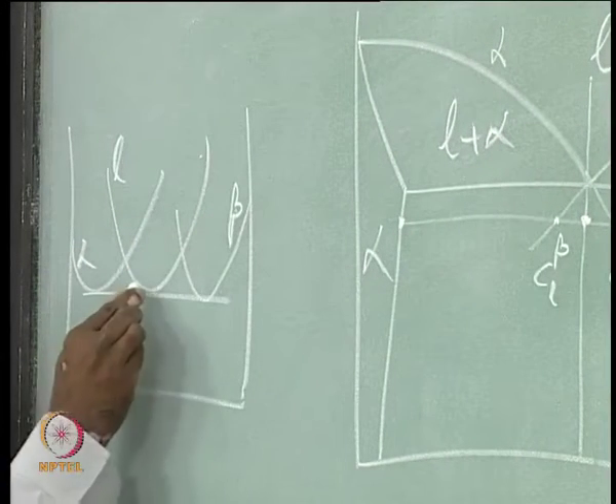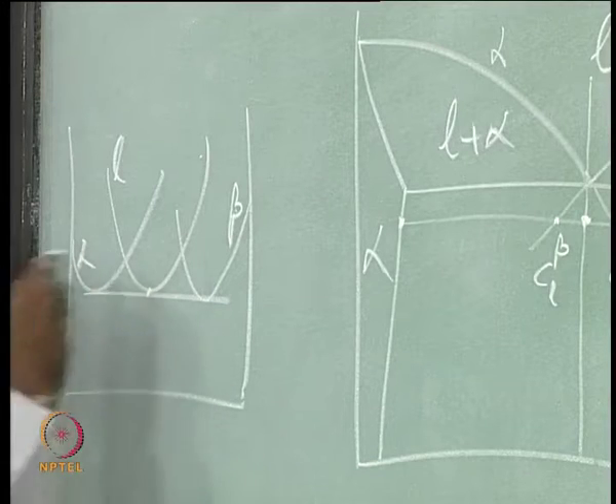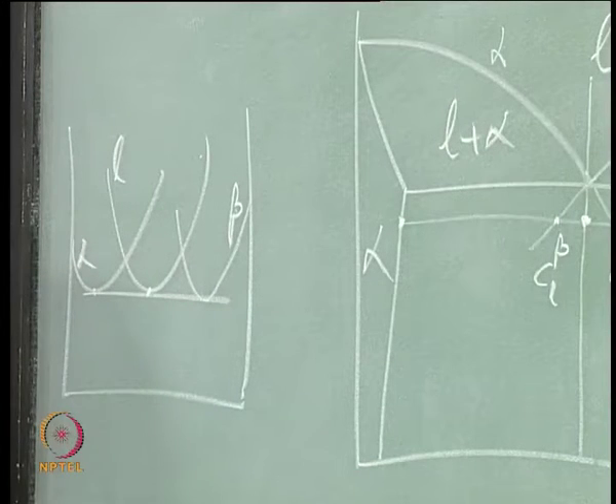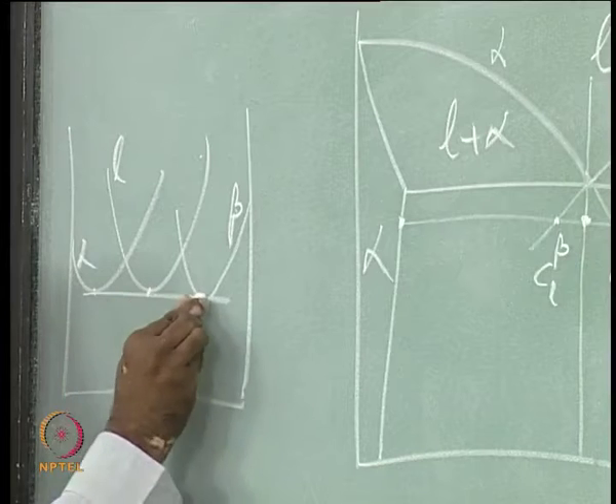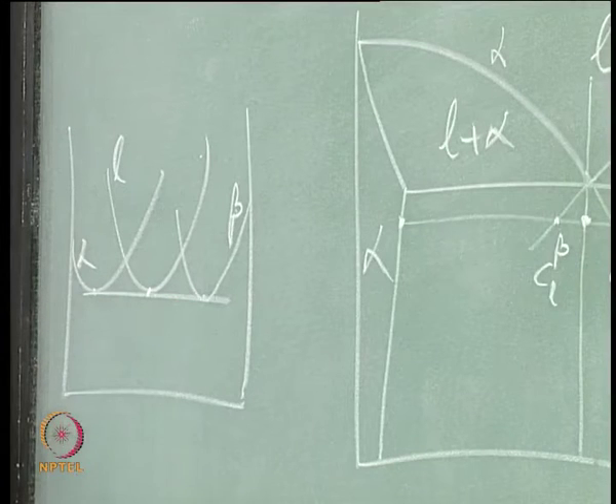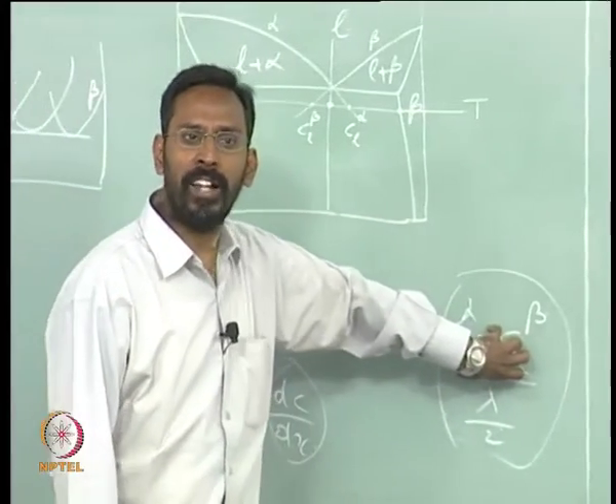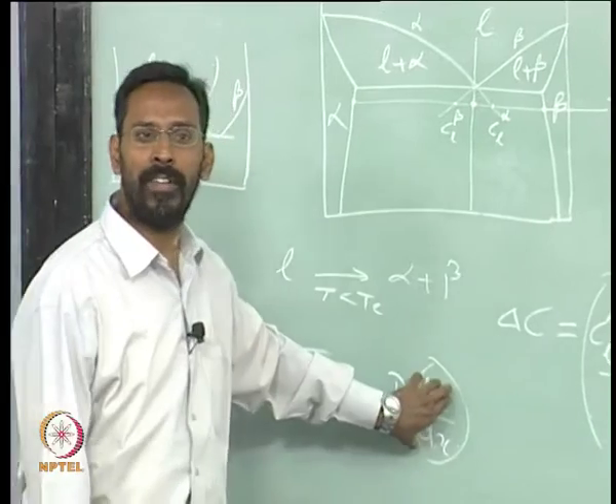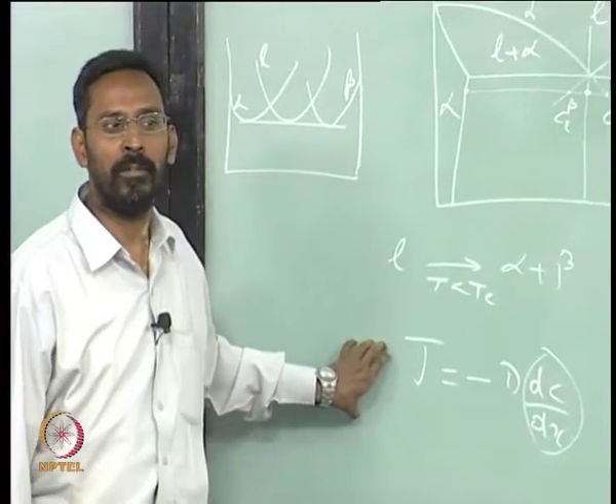So if I am trying to look at what is the composition of liquid in equilibrium with alpha, and what is the composition of liquid in equilibrium with beta, they are the same at the eutectic. Once they are the same, this delta C is 0, and if delta C is 0, the gradient is 0. If the gradient is 0, the flux is 0.